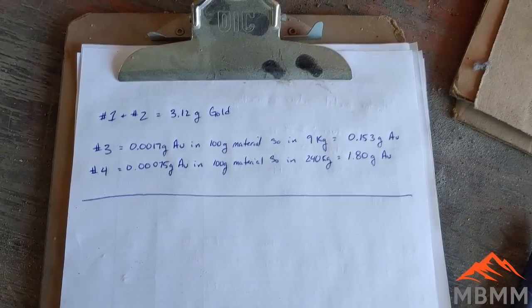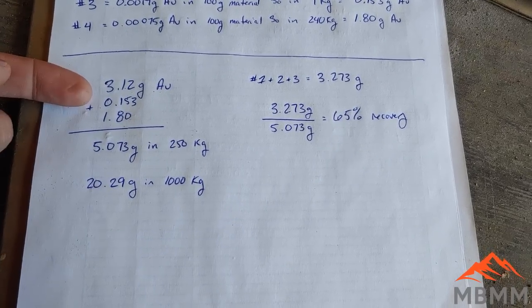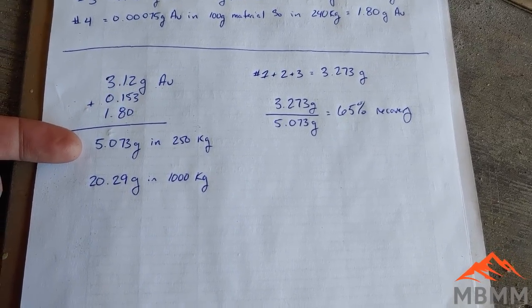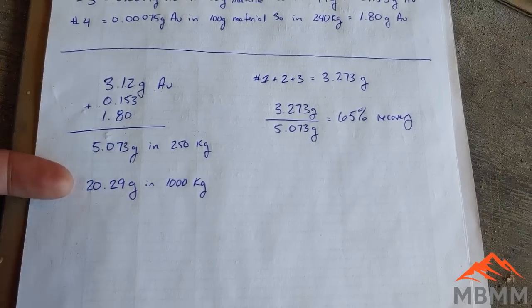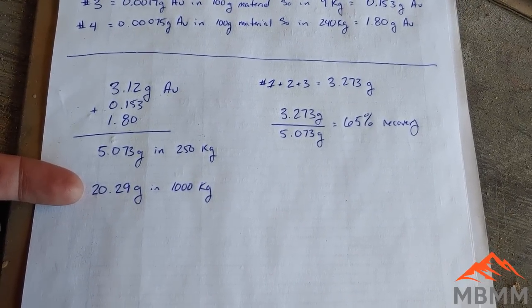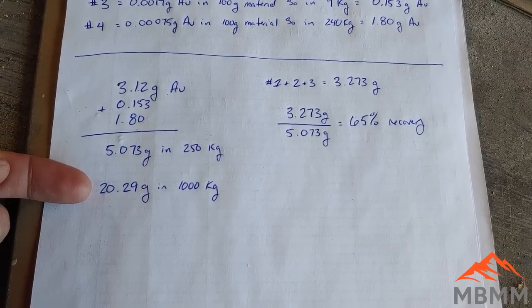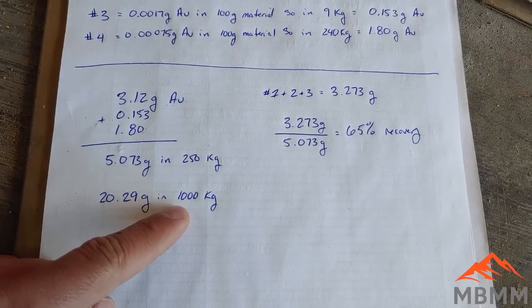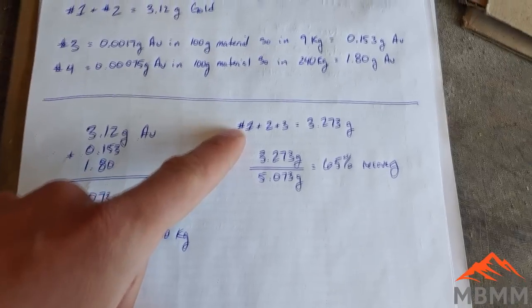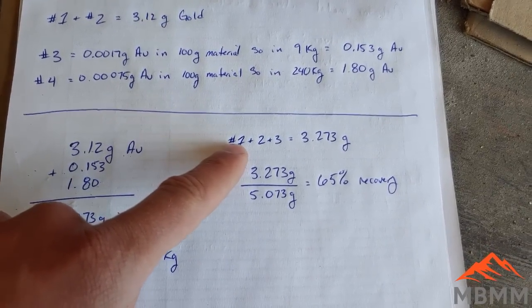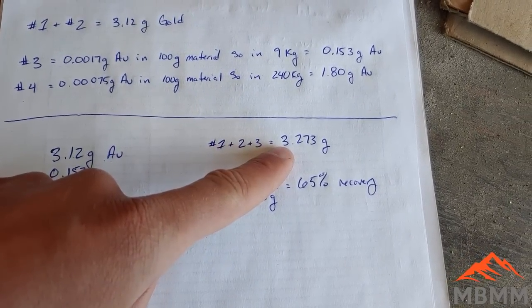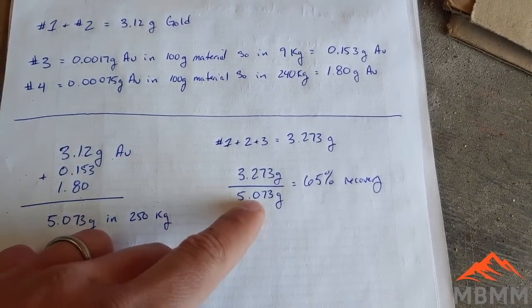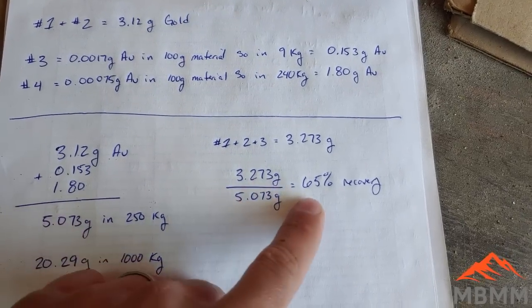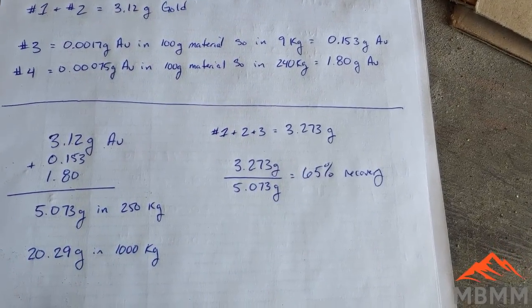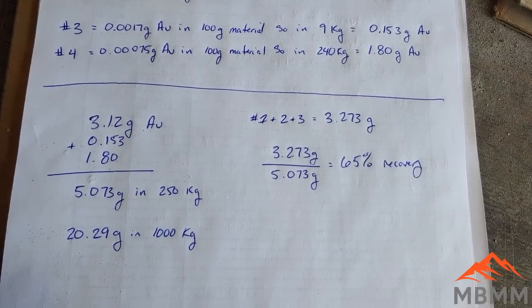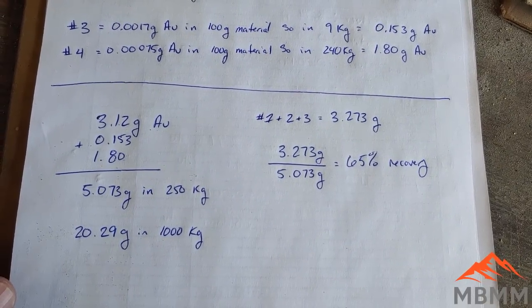Now let's figure out our percent recovery. And here's our total amount of gold in the 250 kilograms. This is a little over 5 grams. So multiplying that out times 4, you get just over 20 grams of gold per ton. So that's pretty good, about 2/3 of an ounce or so. And then our percent recovery, we add 1, 2, and 3 together. We get our 3.273 grams, divide by the total amount of gold, and we end up with 65% recovery. So not terrible for a gravity recovery circuit. I was hoping to get a little bit more.